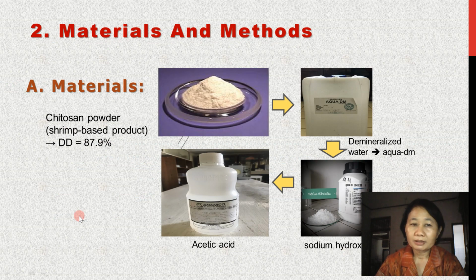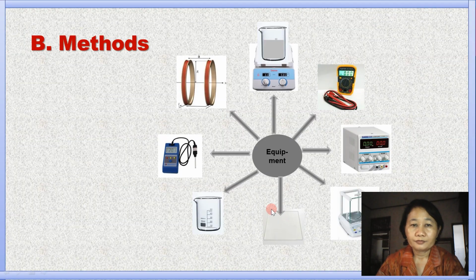For materials and methods. The materials that we require for membrane preparation are chitosan powder, a shrimp-based product with a degree of deacetylation of 87.9%. Also, we use demineralized water for solution preparation, and then acetic acid 1% and also sodium hydroxide that we require during membrane preparation. Then the method of preparing the membrane and delivering the magnetic field direction.